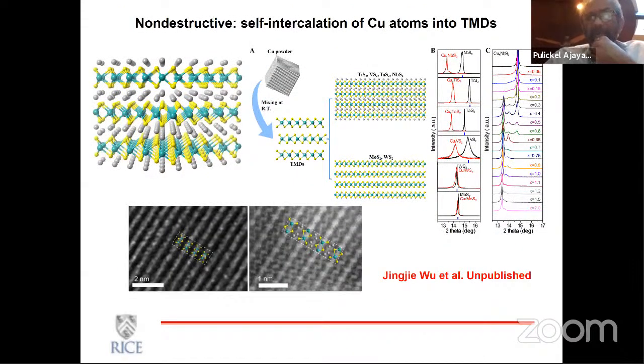Or intercalation. And again, I don't have too much time to go into intercalation, but intercalation has been very popular in layered systems because it's easy to push the layers apart and put other host atoms into these layered systems. And recently we have also done some non-traditional intercalation approaches. In fact, mixing copper and some of these TMDs and heating them to a certain temperature allows you to nicely intercalate the metallic atoms within the host galleries. So again, these change behavior significantly.